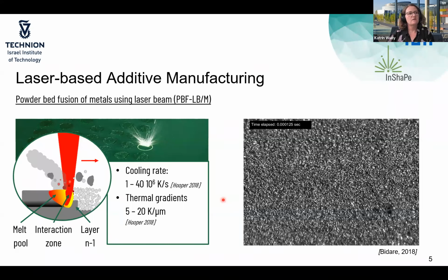So this is for the standard process using a Gaussian beam profile. What we have now conducted is what happens if we change the beam profile to this ring-shaped beam profile. It's more of a donut profile with the index 4, 5, and 6. And what you can see is green is always the process window for the standard Gaussian beam profile. On the y-axis, the laser power, and on the x-axis, the scan speed.